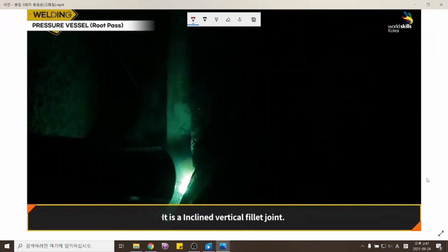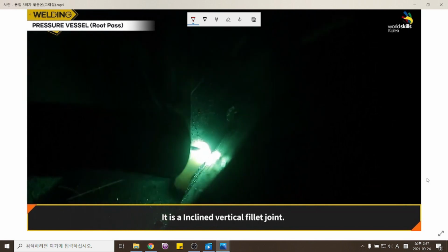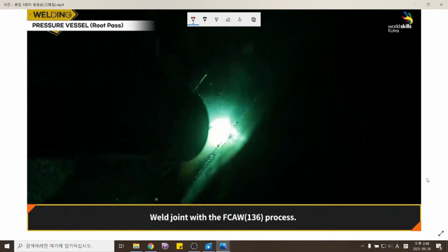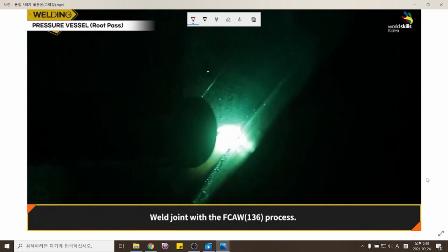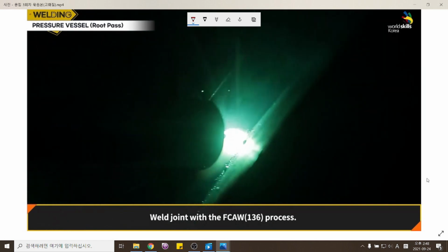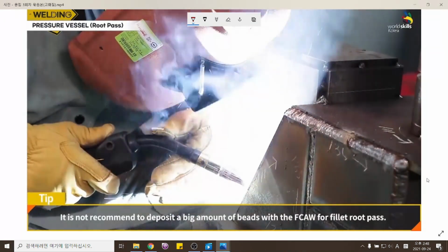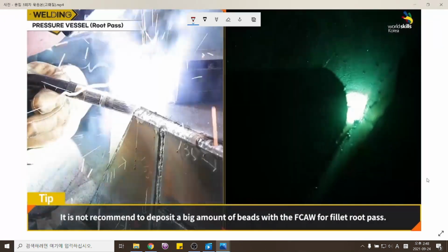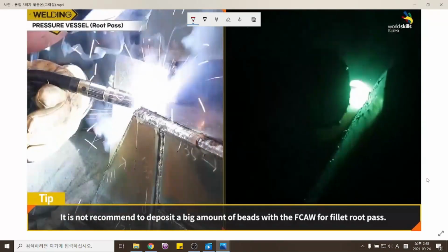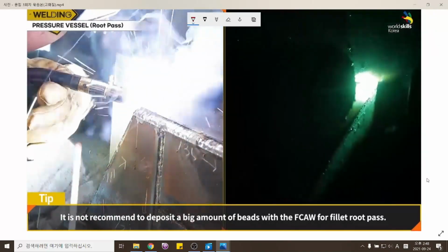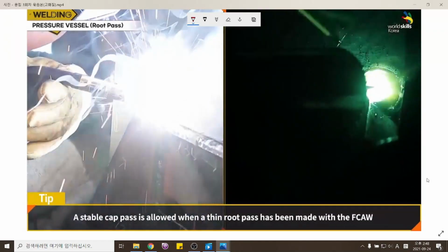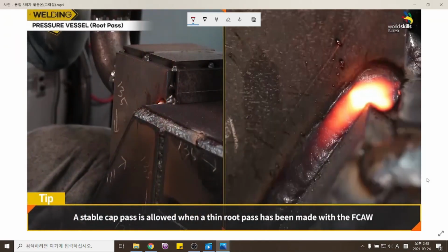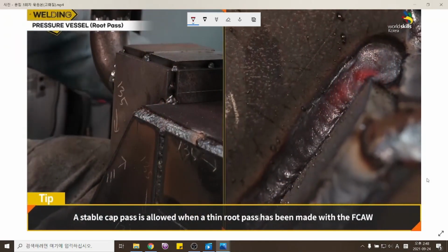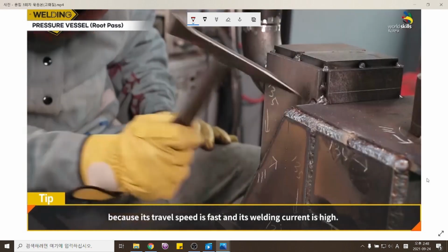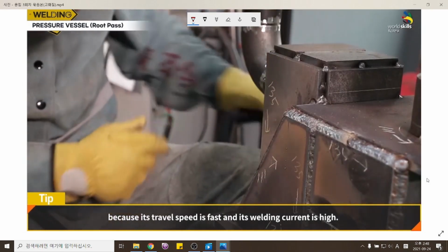It is an inclined vertical fillet joint. Weld the joint with the FCAW 136 process. It is not recommended to deposit a big amount of beads with the FCAW for the fillet root pass. A stable cap pass is possible when a thin root pass has been made with the FCAW because its travel speed is fast and its welding current is high.